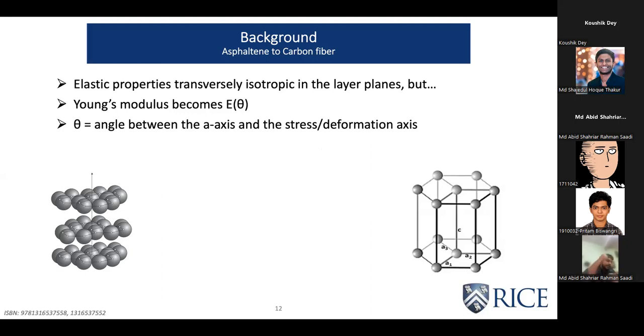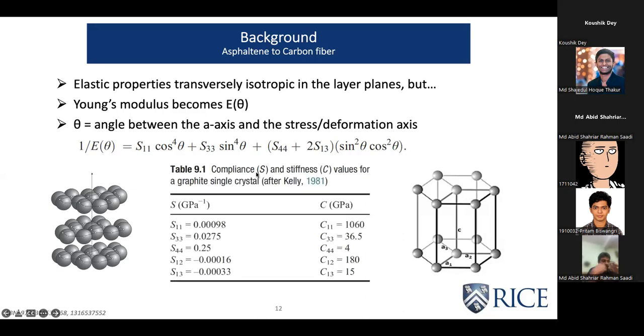or the axis along which you do the tensile measurement. And this is often presented in the form of this equation where you see the relation between the modulus and theta, and S is the compliance here. And people have already calculated the mechanical properties, basically the compliance and the stiffness, in this case for graphite single crystal materials along different directions, and have got different properties.